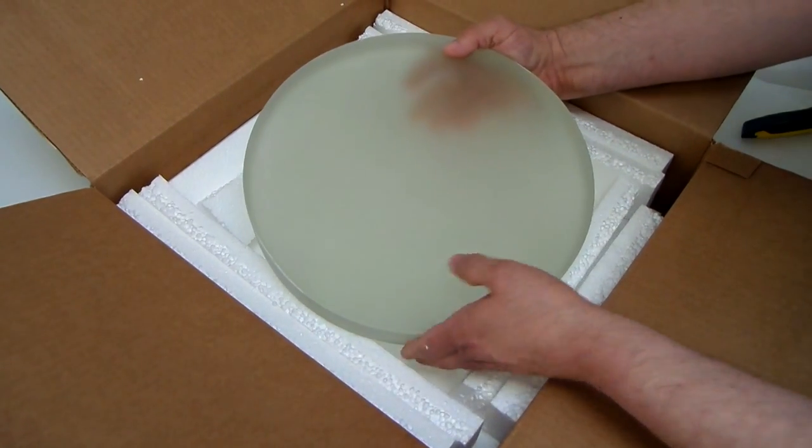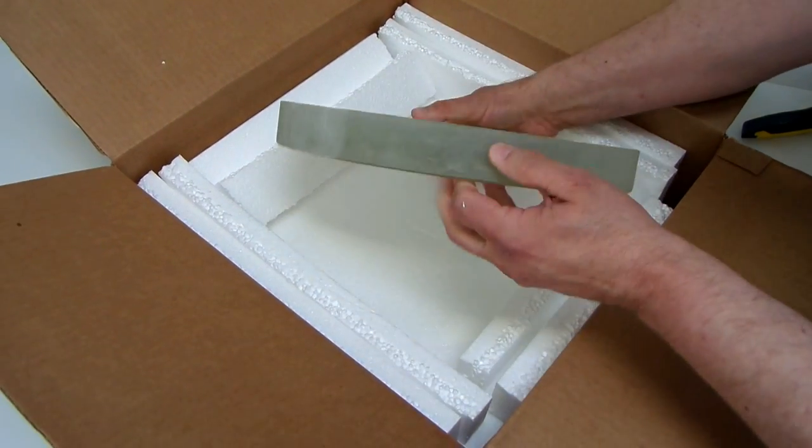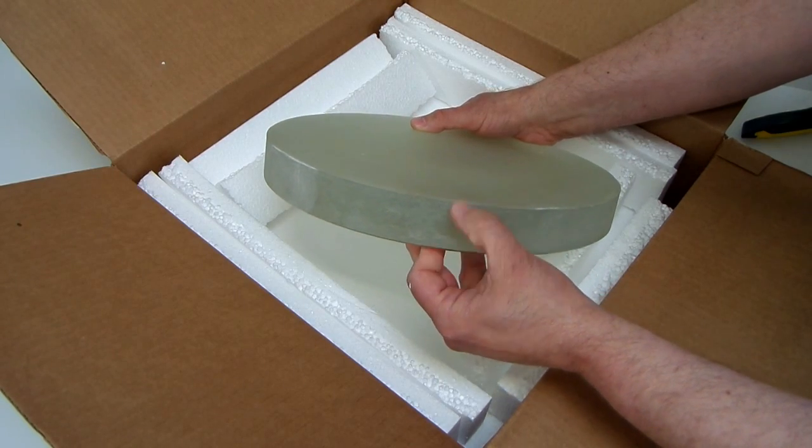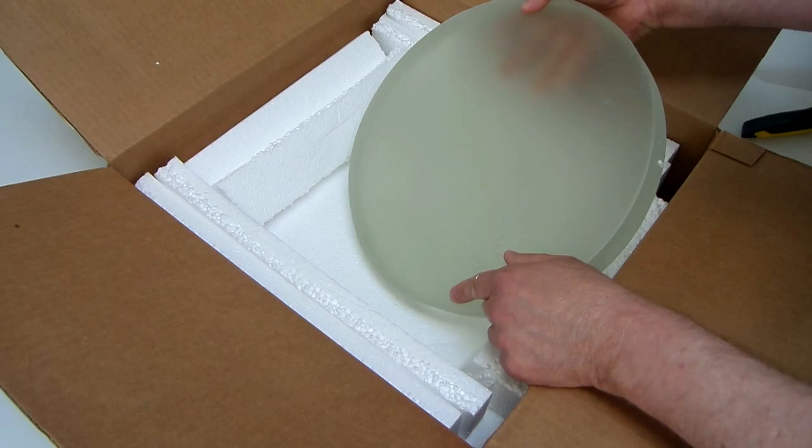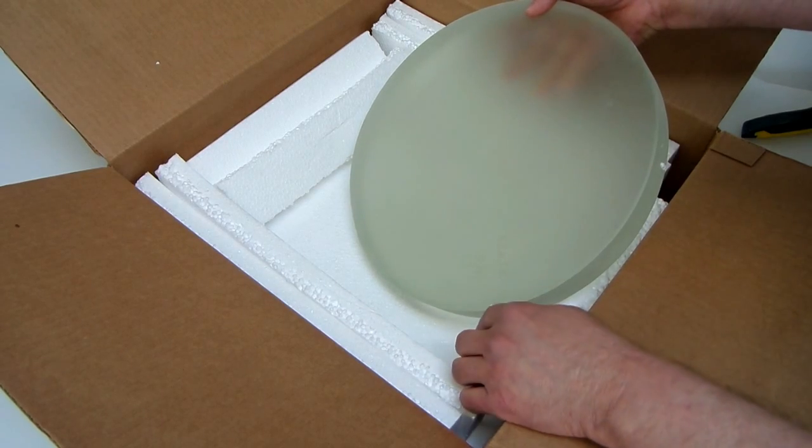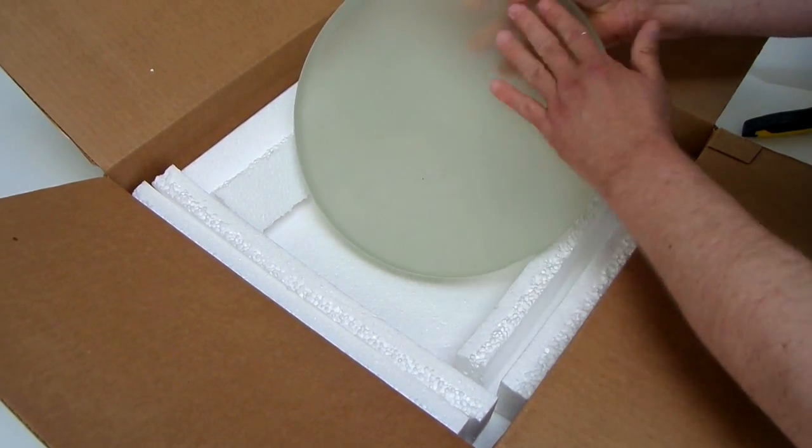It's been pre-generated 12 inch diameter. It's supposed to be. We'll measure that next. 35 millimeters on the edge and the top surface should be generated to an F4.9 1500 millimeter curve and the back was Blanchard ground flat.